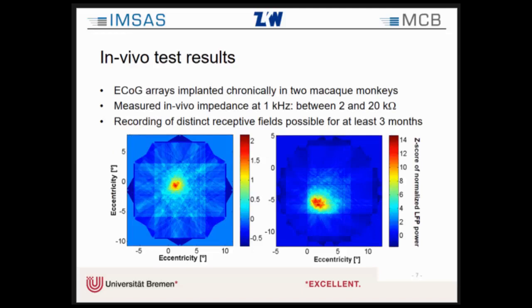So we implanted 2 arrays in 2 macaque monkeys chronically. We measured in vivo impedance at 1 kilohertz. The impedance range was between 2 and 20 kilo ohm, which is quite a bit higher compared to in vitro. And the monkeys were trained to perform a fixation task. So they had to fixate a cross on the screen, and during the fixation, a bar was moving over the screen, and the activity in the cortex was recorded simultaneously.